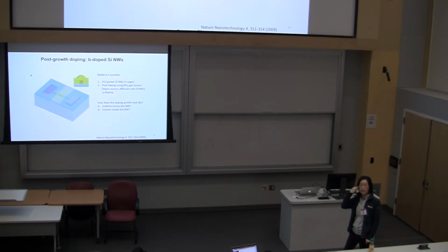So, an example of post-growth doping. First, grow nanowires, silicon nanowires, and then use BCl3 gas source. Just basically subject these nanowires to this gas at some elevated temperatures. Question: if you did this post-growth doping, how do you think the doping profile will look like? In terms of the cross-section, will the dopants be uniformly distributed in the wires, or do you think that it's uneven? Uniform.